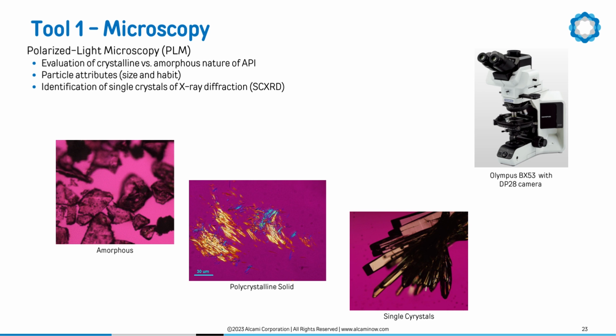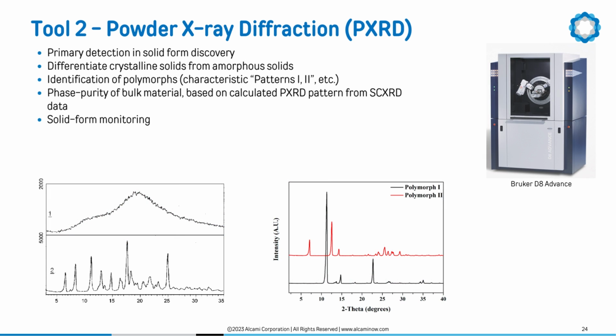PLM can also distinguish crystals based on size and habit, as well as identify single crystals for X-ray diffraction analysis. Next, in the solid-state toolbox is very powerful powder X-ray diffractometer, which we use as primary detection method in the discovery of polymorph salts and cocrystals. PXRD also differentiates crystalline forms from amorphous, but in addition, it generates a characteristic pattern that is used in identification of crystalline forms. PXRD can also be used to assess phase purity of bulk material and is used in batch monitoring to demonstrate form control under various process conditions.